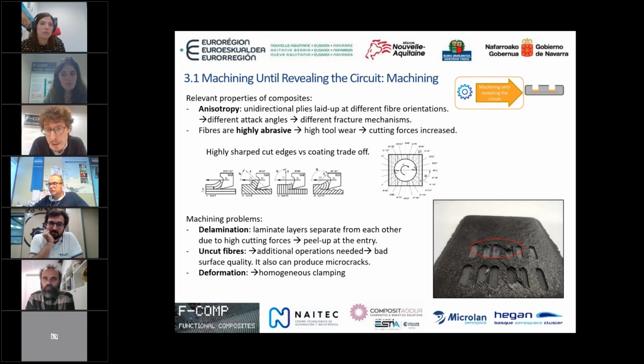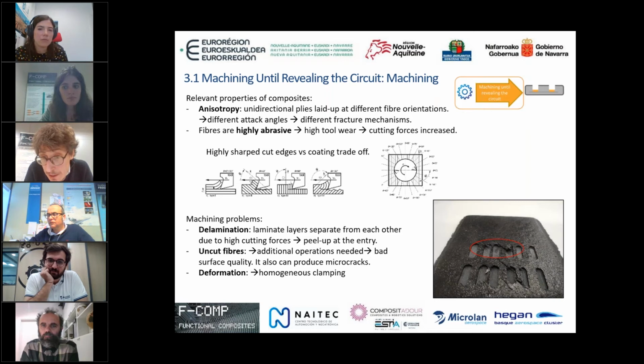Some are more promising than the others, but broadly it can be concluded that we have delamination if we do not cut it properly. You see that the samples in the middle are more damaged than, for example, the ones on the right. There are uncut fibers. That is something that has to be solved because they can produce micro cracks. And the deformation of the part when doing the cutting is something very important, as it generates as well the imbalance of the part, generating deformations that are unwanted for a proper mechanization.